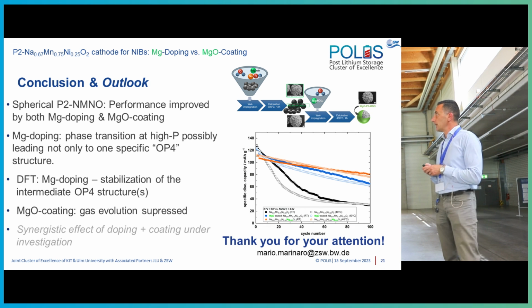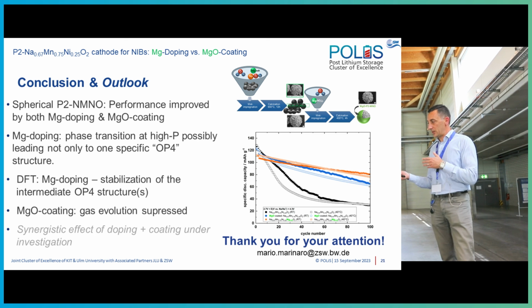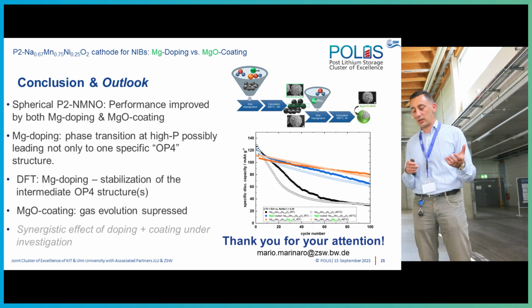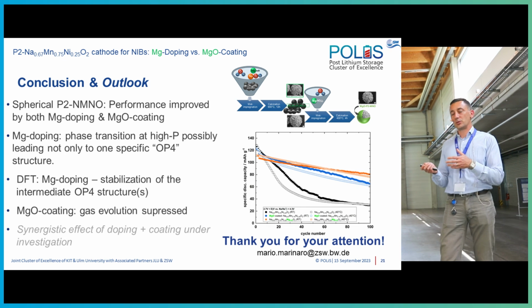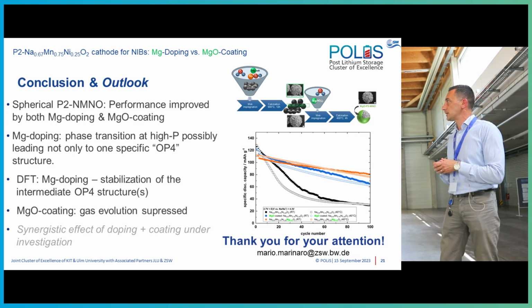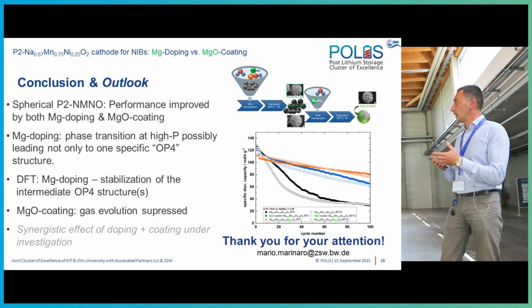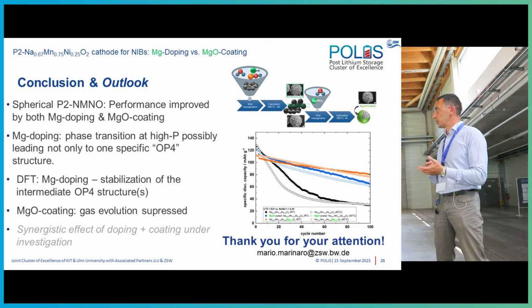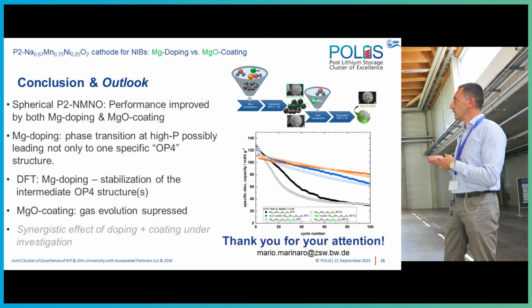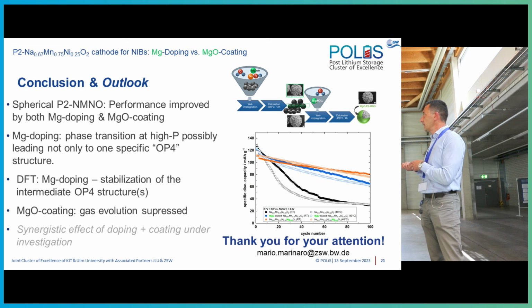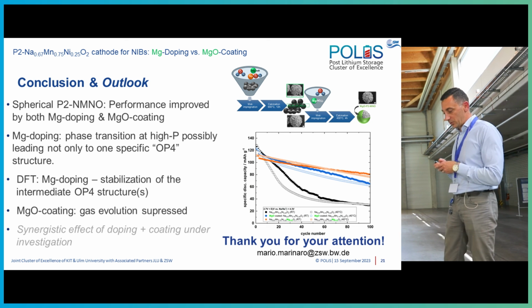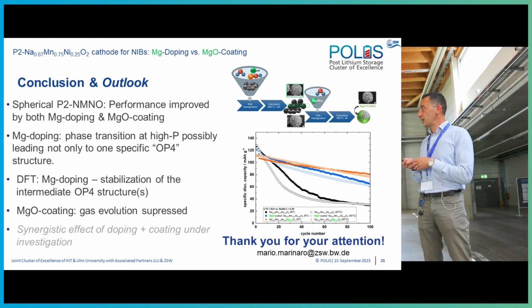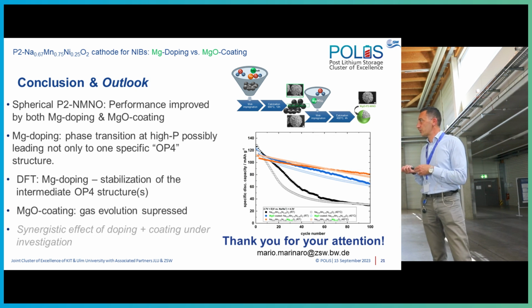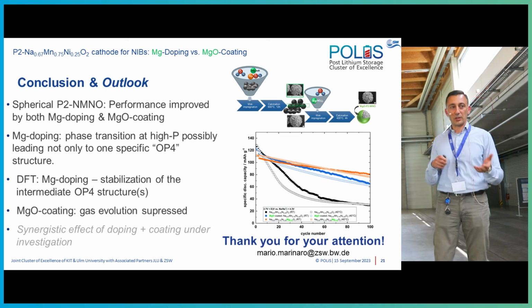So the conclusion is that we compared the magnesium doping and the magnesium oxide coating on P2 layered oxides. We have seen that there is an impact and an improvement of the performance. This is a summarizing graph. Still, the doped material performs better at room temperature and also at 40 degrees C. Now the question will be whether we have some synergistic effect, so coating plus doping.